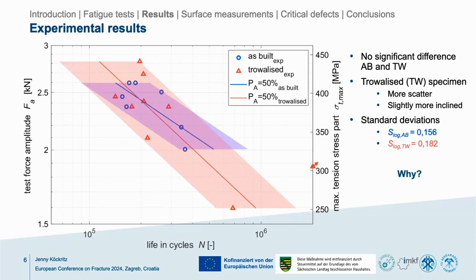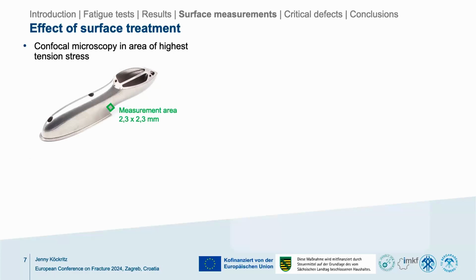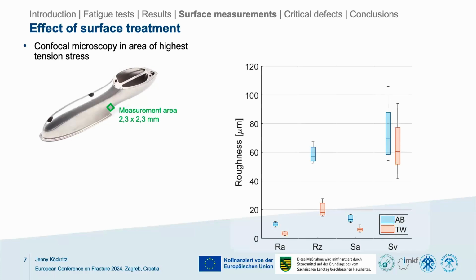So the question is why? First we're going to look at the surface measurements that we conducted. The surface measurements were done in the area of highest stress at the lower edge with a confocal microscope. And the results are displayed in this diagram. Surface measurements were done for all specimens. So the first thing we can see on the left side here, the line roughness values of Ra and Rz did actually show an improvement with the trowalizing. So we reduced Ra and Rz. However, if we look at the values of the deepest valleys in the measurement area, we see a big scatter and not a huge difference between the two.